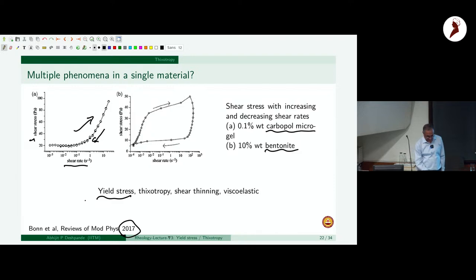You have a yield stress, but when you go forward and come back, they exactly trace the same points. And so the evolution of structure is not a significant phenomenon here. This is just a yield stress system. So the breakage and reformation timescales and evolution of structure, especially the rebuilding timescales, are quite fast. And so you basically come back the same way, because this is one important way of looking at a thixotropic system. You say, I'll measure stress as a function of strain rate, and what you see is